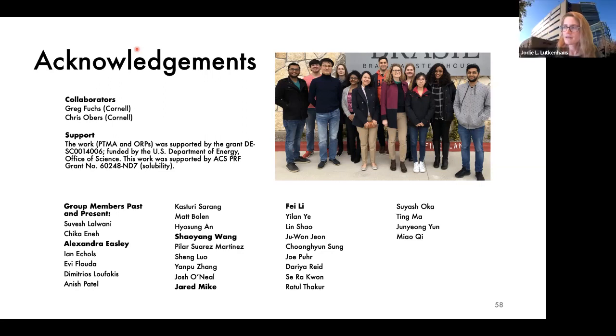Yeah, if I understand the question correctly, when we were doing our solubility parameter studies, we were considering the true state of the polymer with those three groups. So when we were calculating the group contributions that are reported in the paper, those were back calculated considering the true composition of the polymer. So we did our best to capture those little details.